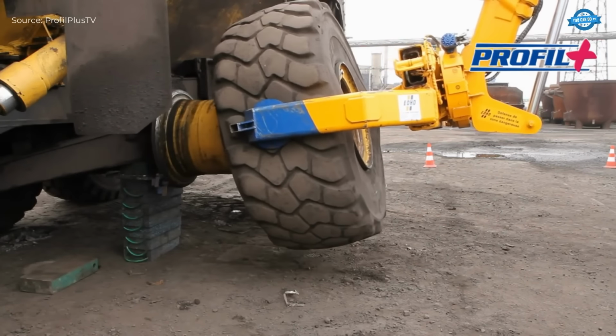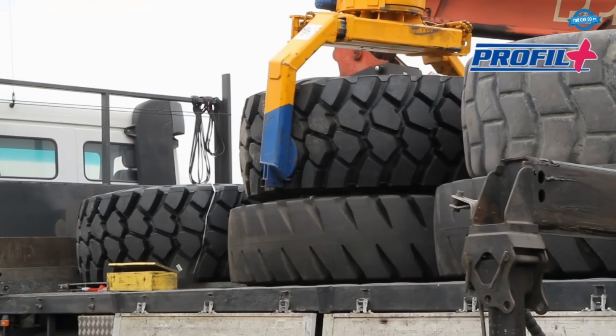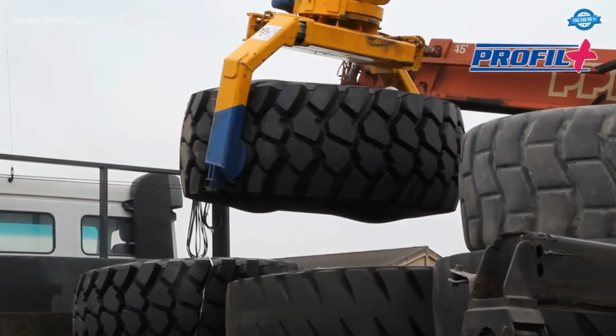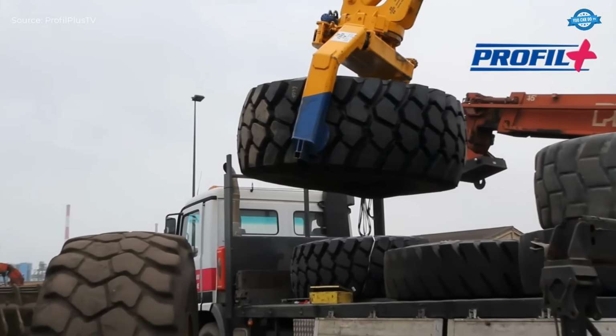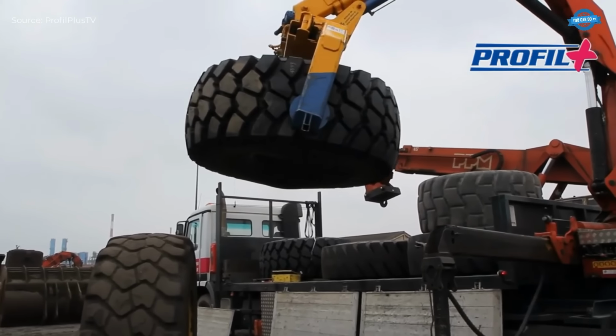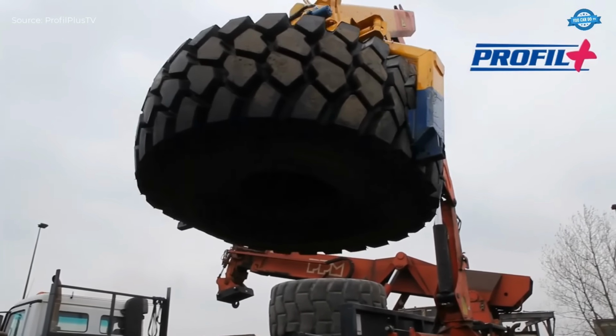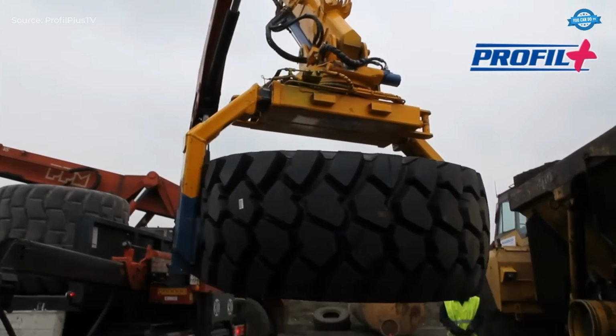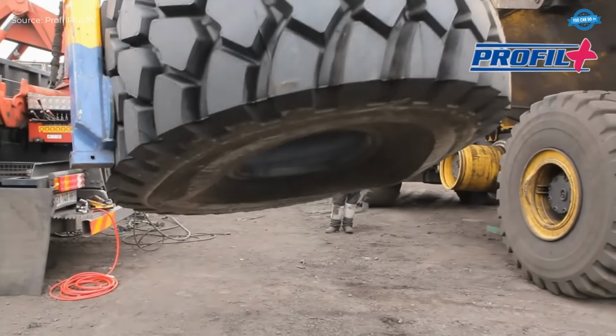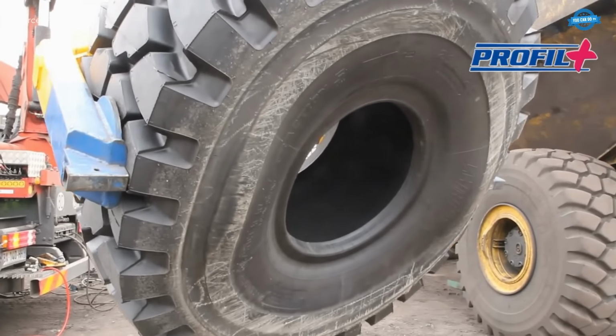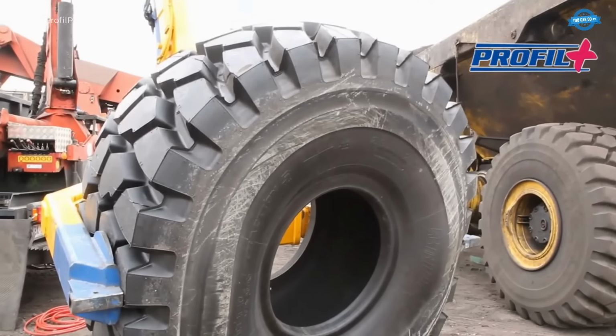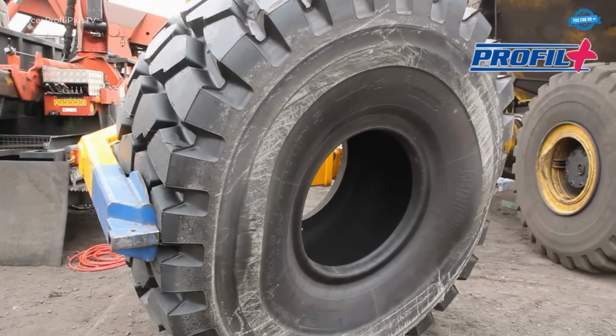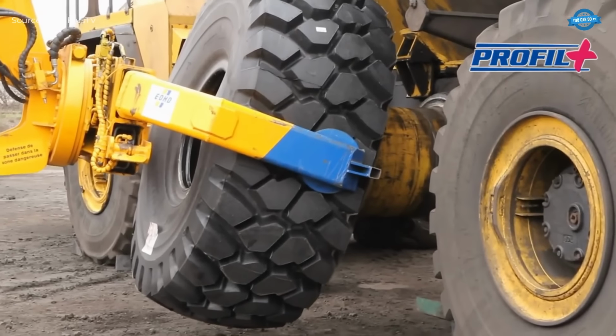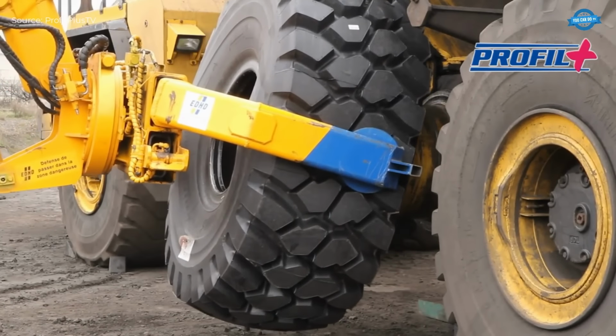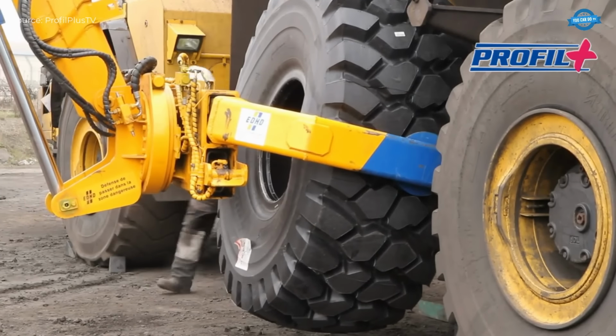In this specific case, the crane was equipped with a specialized grab designed to handle the weight and size of the OTR tire. These tires, typically ranging from 24 inches to 63 inches in diameter, can weigh anywhere between 200 kilograms and 5,000 kilograms, depending on their size and construction. The OTR tire involved in this intervention was approximately 49 inches in diameter, weighing around 1,500 kilograms.